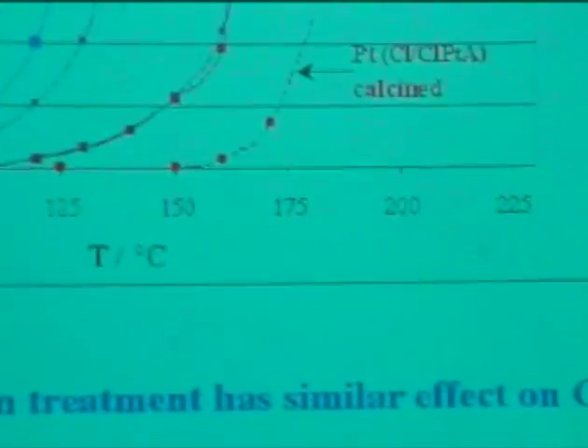If you do it for 3 hours or 4 hours, your chlorine is waiting right there and your support ready to jump onto the metal. Okay? What is there? Okay, this is the chloroplatinic acid, again calcined. It's less active than the one without the chlorine. So everything is consistent, providing that you take that into account.